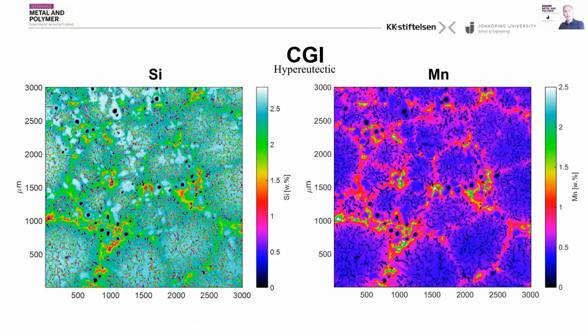On the left here, we see another map where we have measured the concentration of silicon of a compacted graphite iron. And here we can also compare to the microsegregation of manganese on the right. Just to illustrate that the silicon segregation patterns often correlate quite well with the segregation of other elements, such as manganese. Here manganese segregates inversely: manganese is found rich in the areas where silicon is impoverished, and it's found in low concentrations where the silicon concentration is rich.